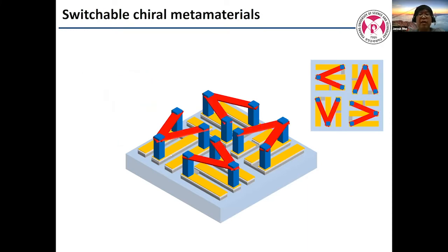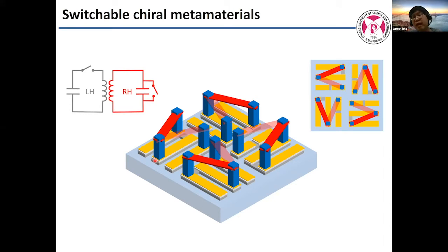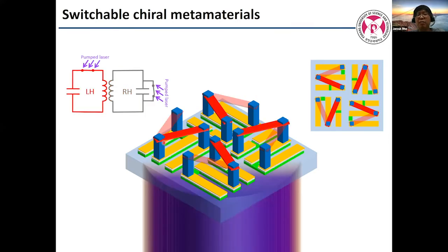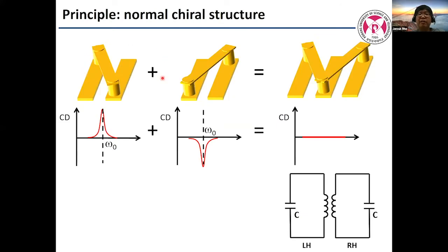So this is based on microfabrication, and we achieved switching performance, from the normal case, a positive index, and then switching on by an external stimulus, by shining light, to change to a negative refractive index. So how do we do that? These are two different chiral structures, left-handed and right-handed. Combining them, each has its own circular dichroism response, plus and minus. Combining these two just cancels, so nothing.